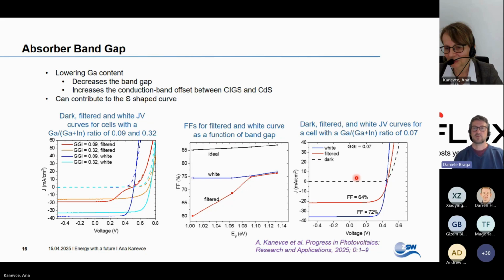A question from Alok. What lattice mismatch is permissible between layers in a tandem solar cell structure? Between layers in the tandem solar cell structure, meaning between the window layers or? I'm assuming in between the two different solar cells, the interlayer. I would not know this. I think all of these layers are lattice mismatched anyway. It's very different than III-V materials, where materials are super high quality, and then even a small density of defects at the interface makes a big difference.